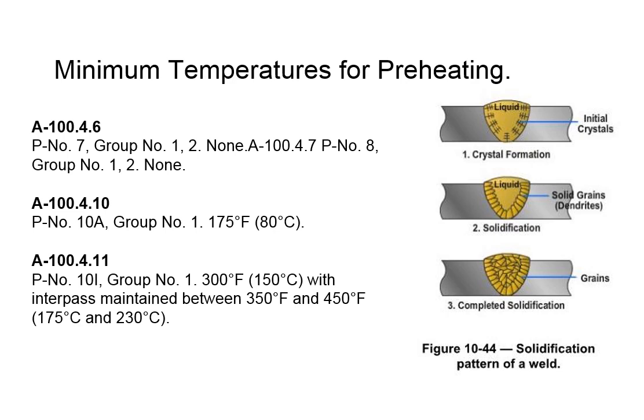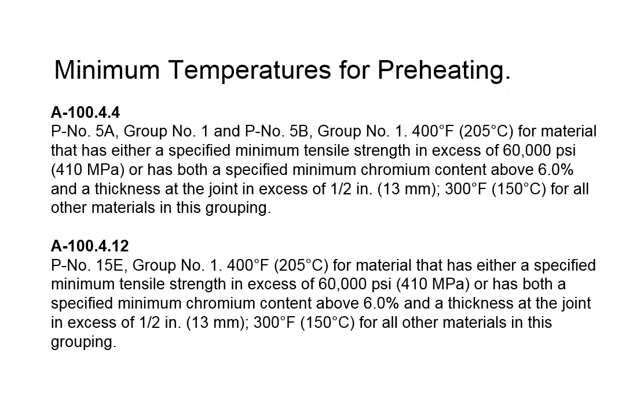I have never really dealt, I don't think, with 10A and 10I, but these are just some examples of what you see as you're going through the welding code, ASME Boiler and Pressure Vessel, Section I. This tells you how difficult some of this stuff is to deal with and what you need to do. They line it out for you for the most part, and with a little bit of research and putting together your documentation, you can get most of the stuff welded pretty readily. But once again, it gets back to weldability. Stuff that needs a 300 degree F preheat and an interpass temperature of 350 to 450 is probably a little more onerous than just welding some carbon steel. Weld it and you're done with it. So here's a couple that I've dealt with in the past that were pretty difficult.